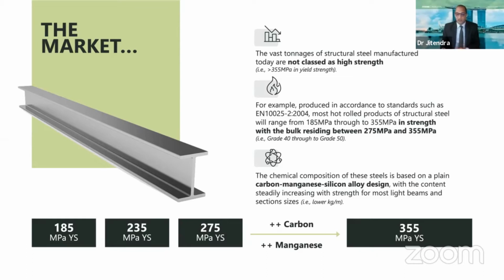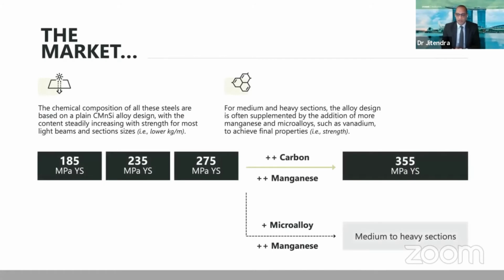As we go to heavier products, which is thicker steels effectively for sections and plate, for example, the chemistry is also further increased to make the properties, as you can see here. The other option steelmakers sometimes have, as we move to 355 sections, is not only to increase the manganese content, but also we do see small additions of microalloying elements, typically vanadium, and occasionally we do see niobium being added, and this is more so for the 355 megapascals.